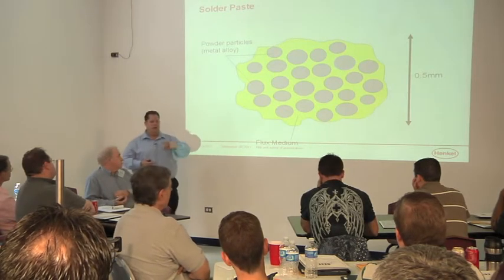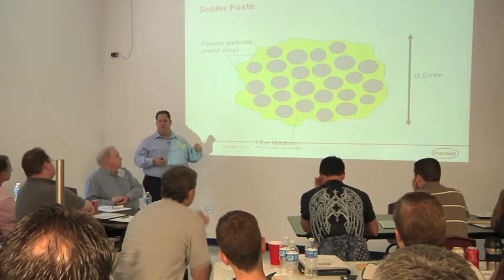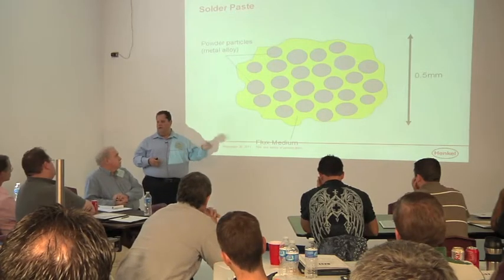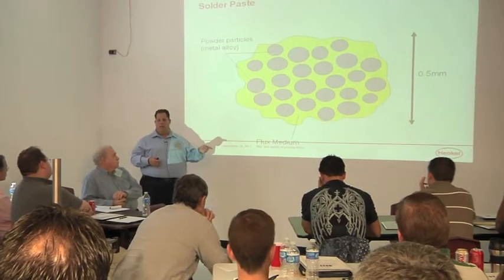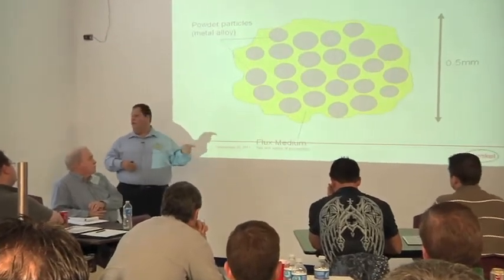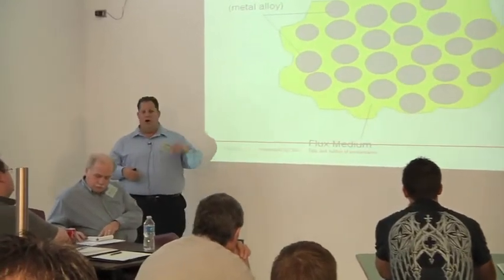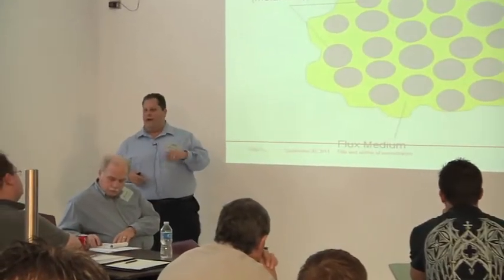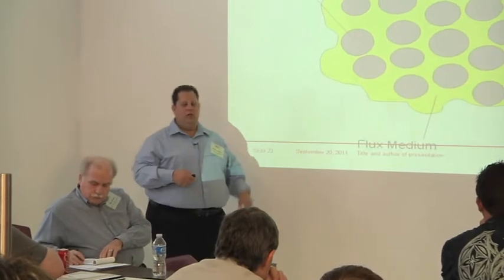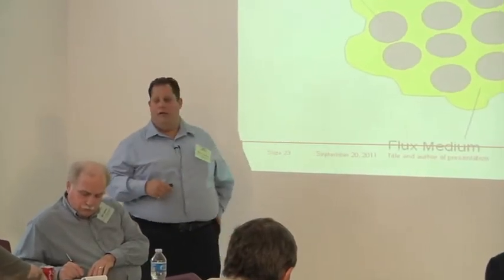It's got to be no-clean, so you don't want to clean it when you're done. So all the activators that do all the work to clean off all the oxides - you want them, after they do that, to not do that anymore. So then they've got to stop; you've got to put in a mechanism to turn them off or to capture them later on. So there's a lot of stuff in this yellow blob here.